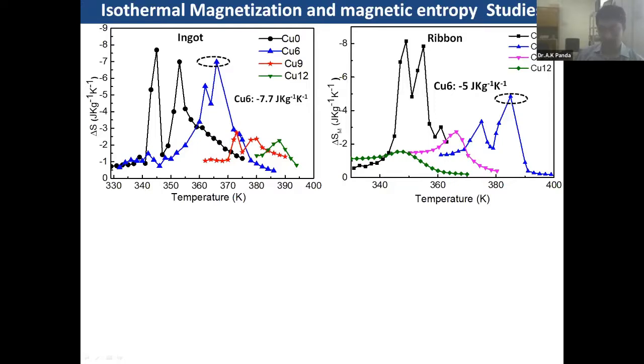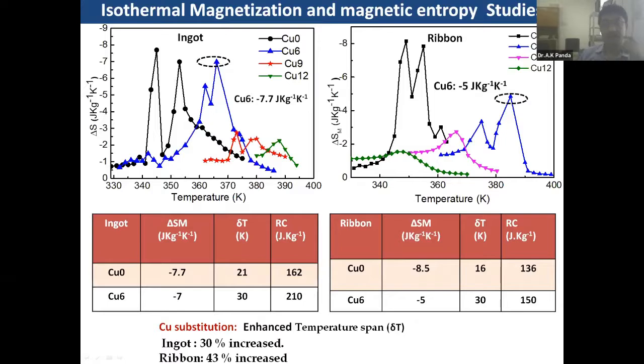So this is something like your ingot and ribbons. When you anneal it at high temperatures, that is for 24 hours and so on, and then you get the copper 0, and this is the entropy. You can enhance the temperature span. You see that in the case of an increase in the copper content, you can increase the working temperature delta T from 21 to 30. Of course, you cannot raise the entropy, but you can raise the working temperature, you can raise the refrigerant capacity even. And the same is true even for the ribbon. Ribbon, it is not very interesting in terms of entropy, but definitely the refrigerant capacity. So there is a combination of these two properties. The delta T could increase 30% in case of ingot, and in the ribbon it could rise by 43%.